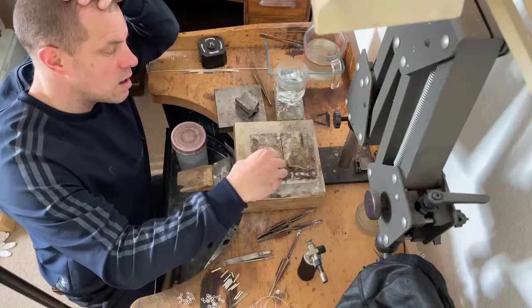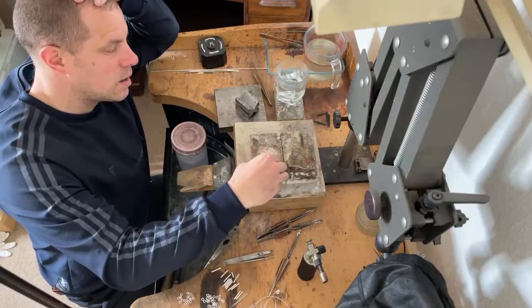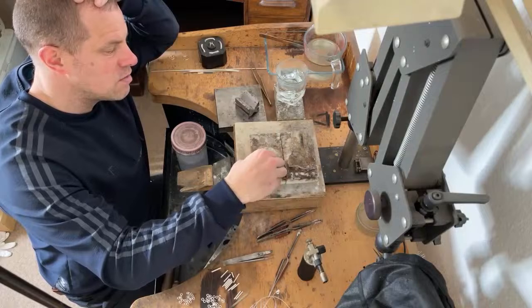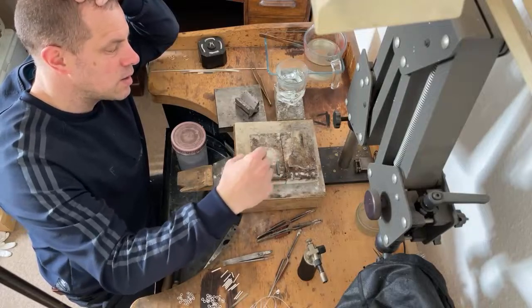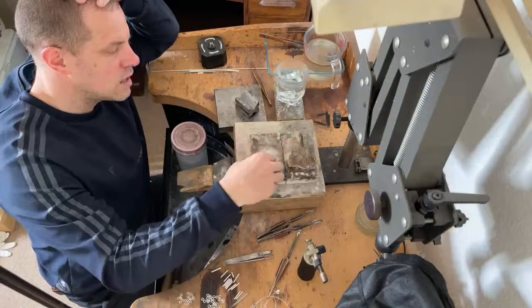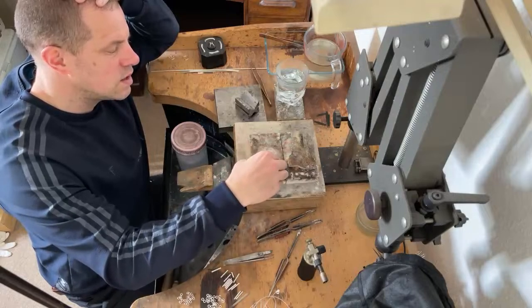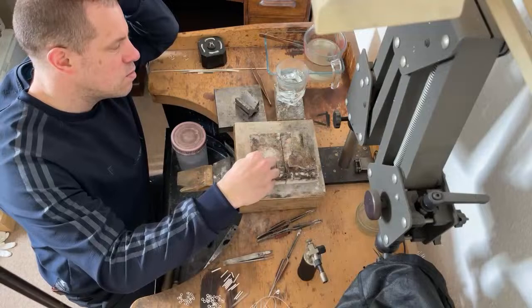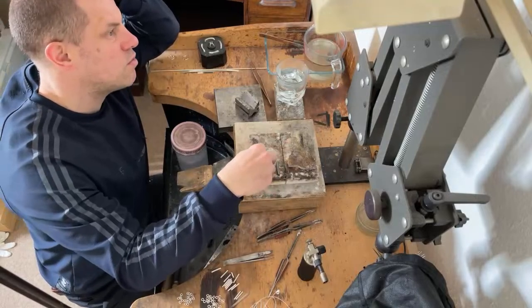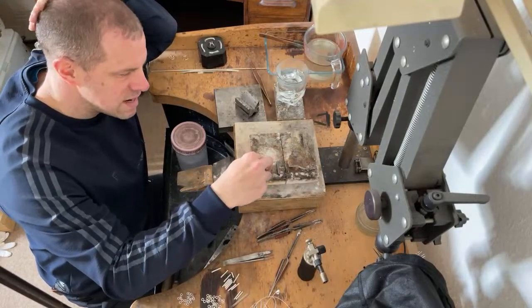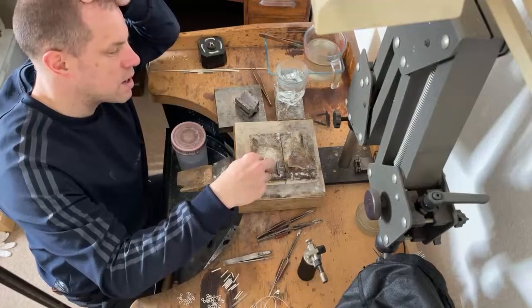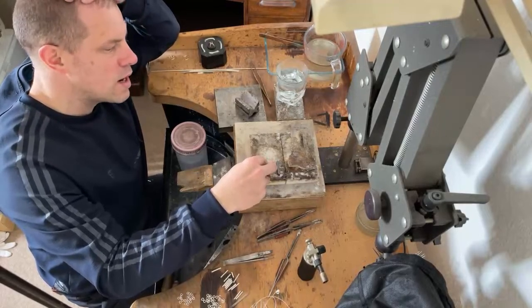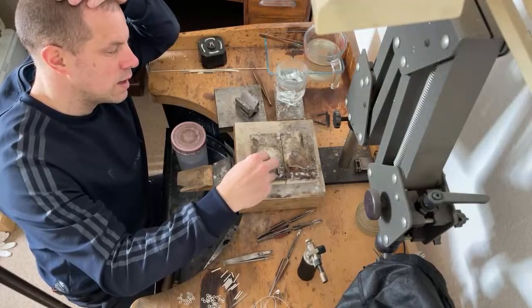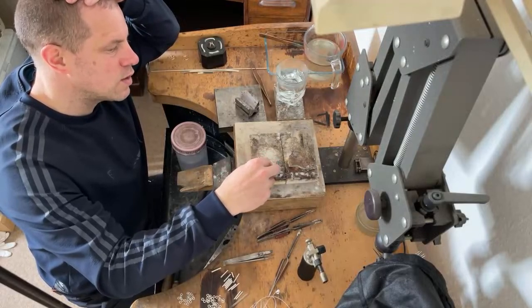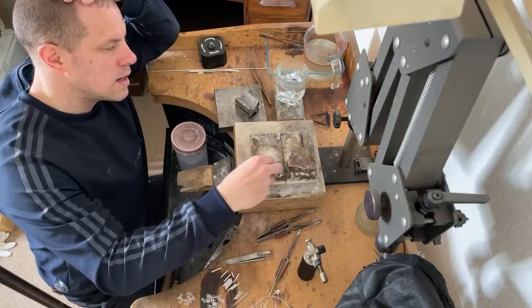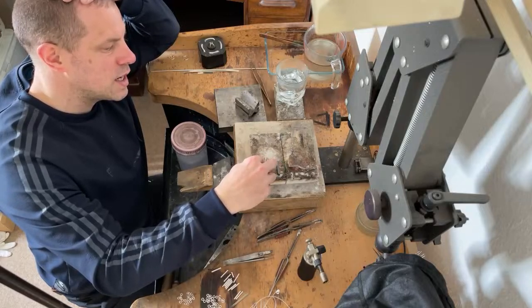Like I say, I was taught to quench solder jobs, and I did for years, and it didn't manifest in any issues. But then you're not generally, apart from ring sizing, there may have been some. The only time you're going to roll out a ring is if you're using a gem ring stretcher, really, and you're not rolling it out that much or in its entirety. But yeah, if you quench silver ingots, which we were doing for a period, then roll them out, you end up with porosity in hand poured ingots.